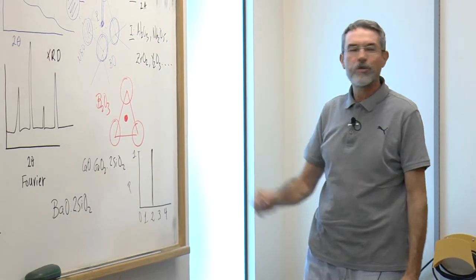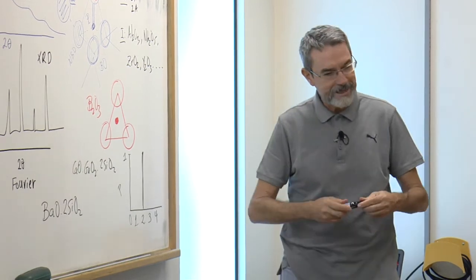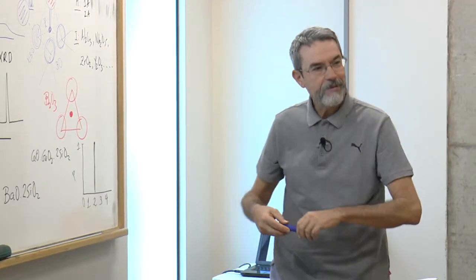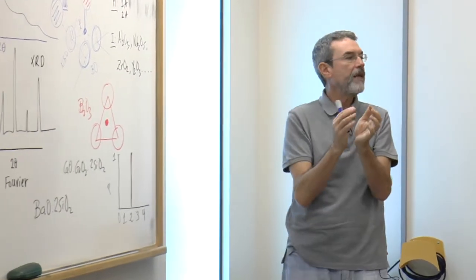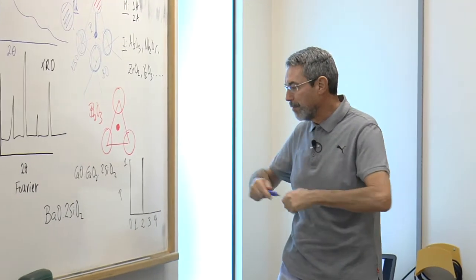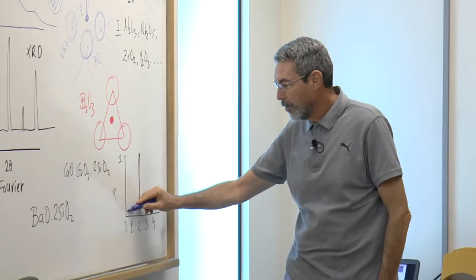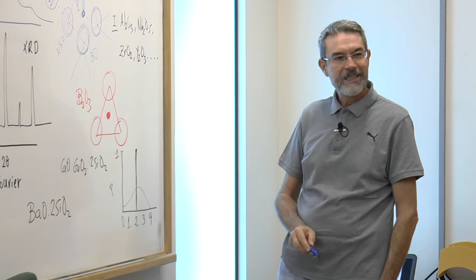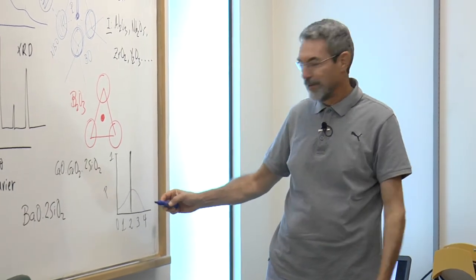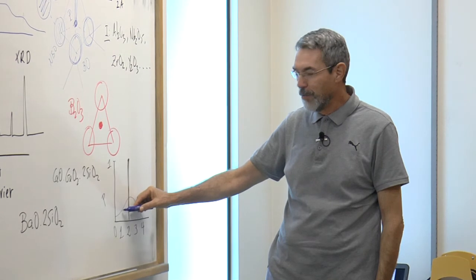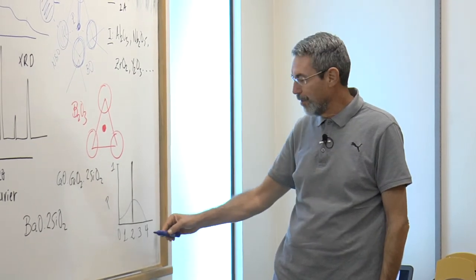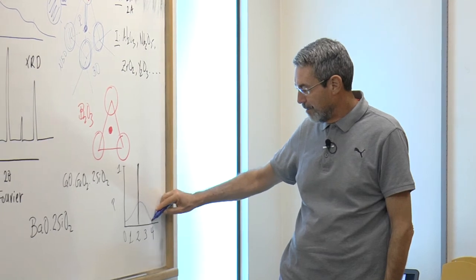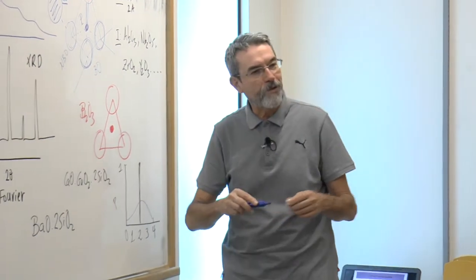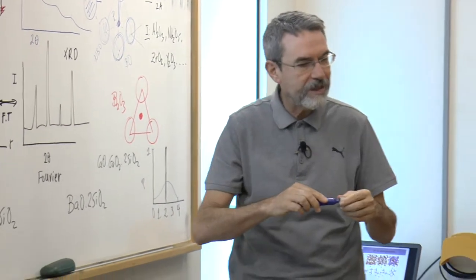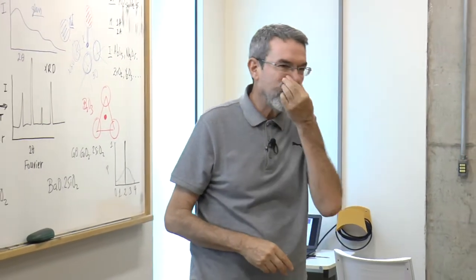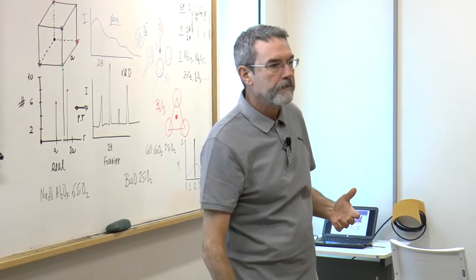Your crystal will be a Q2 crystal. But your glass, if you do an NMR, this formula only gives the average. So the average will be here, but if you do an NMR, you probably have something like this. Some 30% Q3, some 20% Q1, some 10% Q0, even some 10% Q4. There is a distribution, and the structure is not clean as in the structure of a crystal.